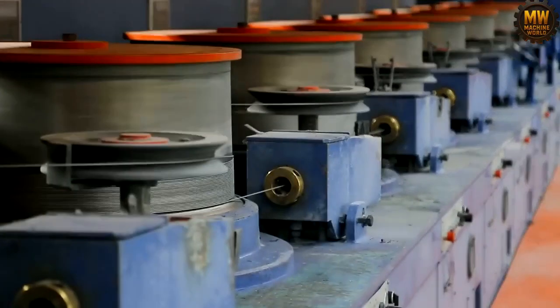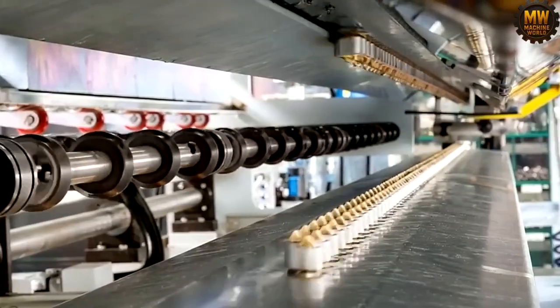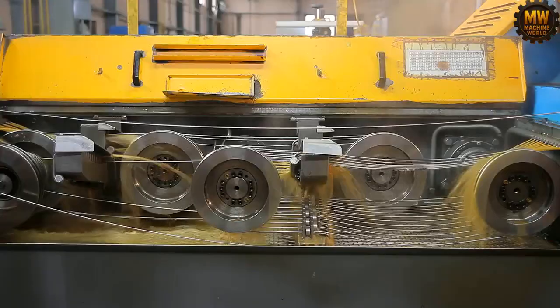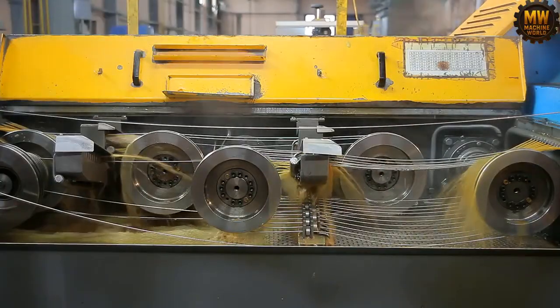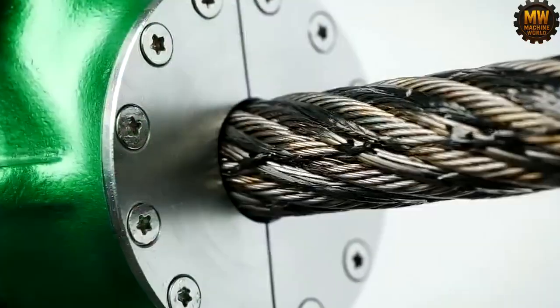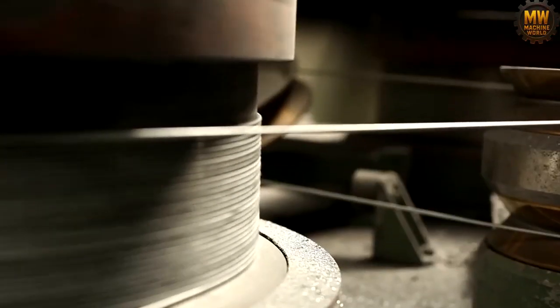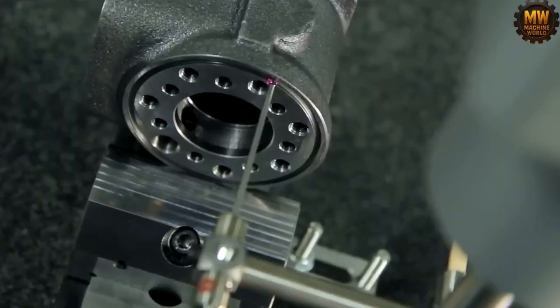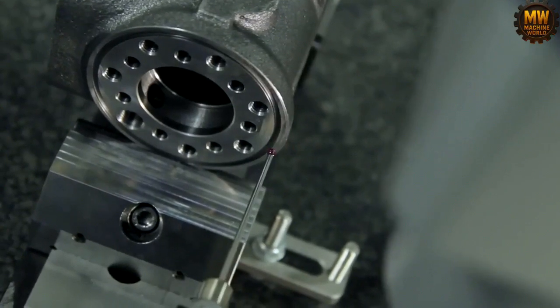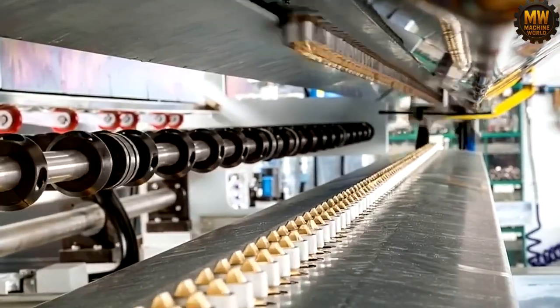The thread flies through the drawing blocks at speeds reaching 30 meters per second. Red laser beams cut through the mechanical haze. These optical sensors continuously scan the thickness of the flying line in real time. The operation demands absolute perfection. The allowed margin is 0.001 millimeters. That is a deviation 50 times thinner than a single human hair.